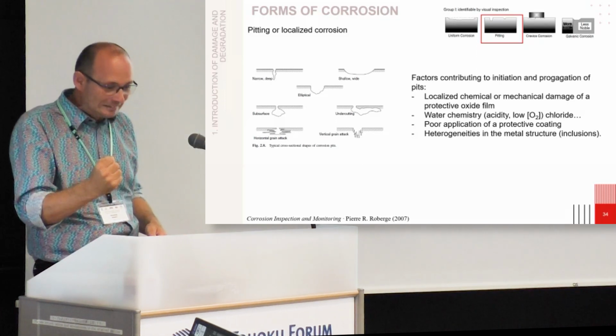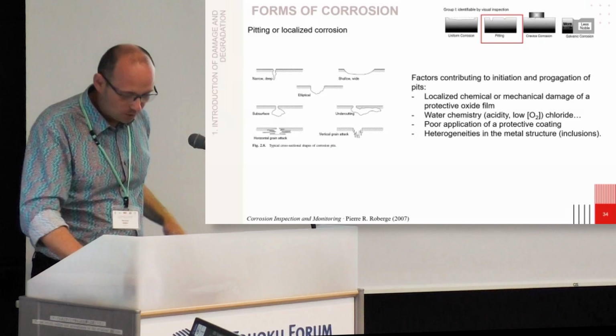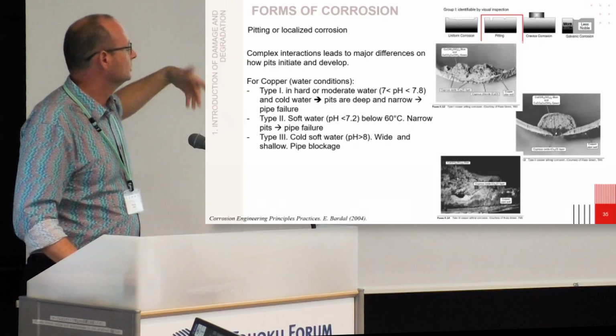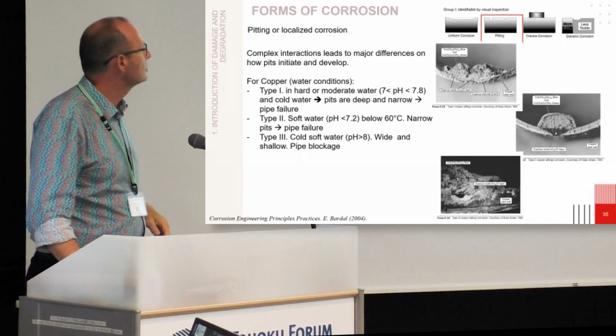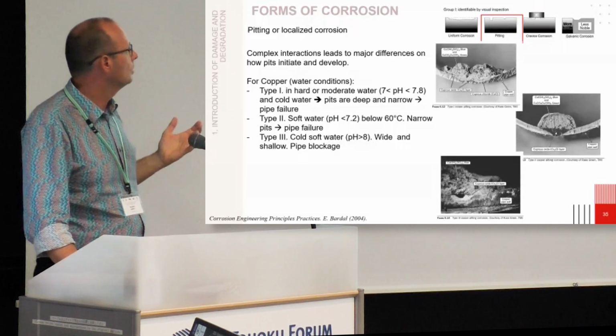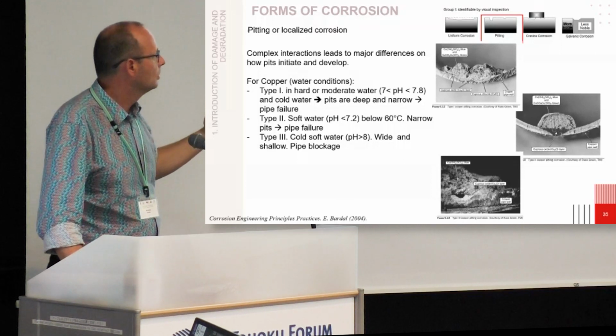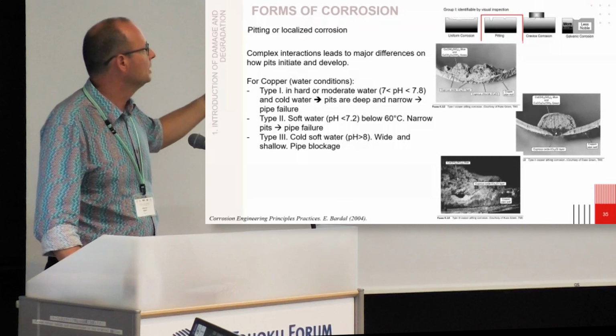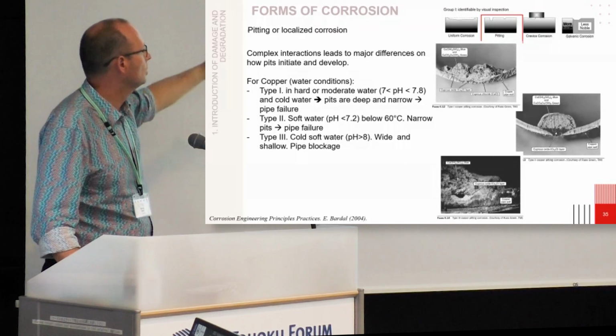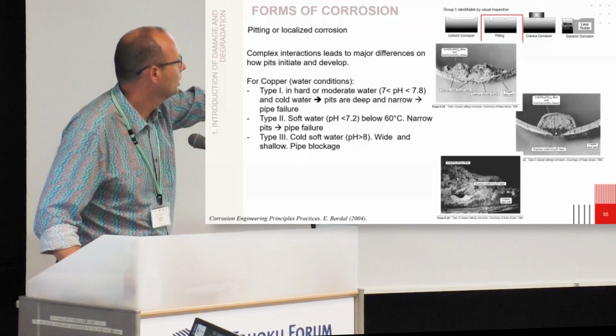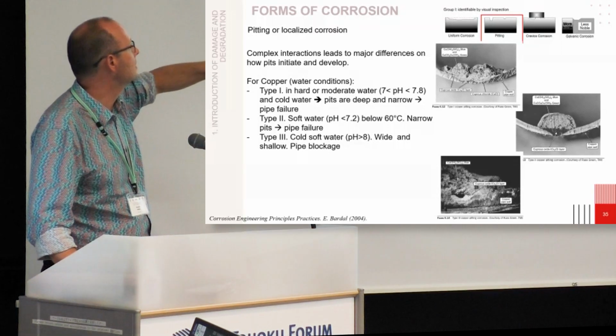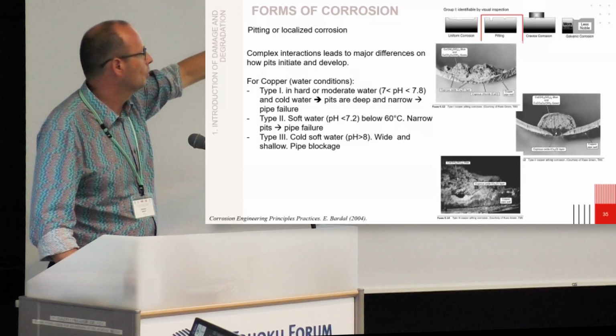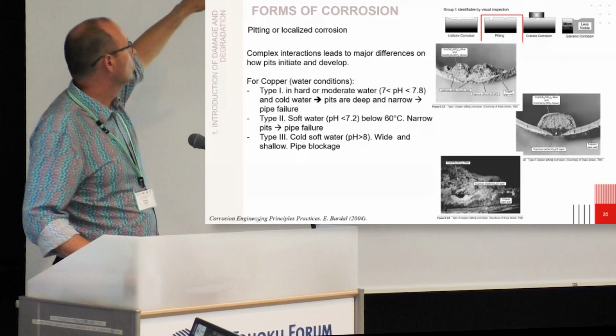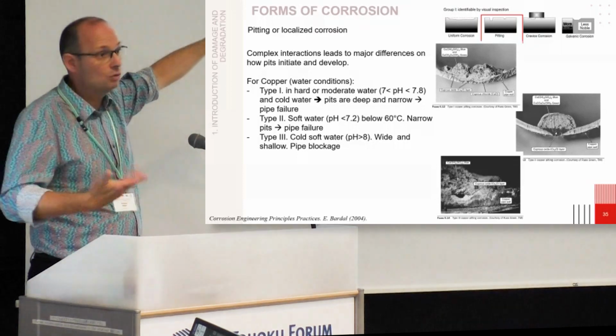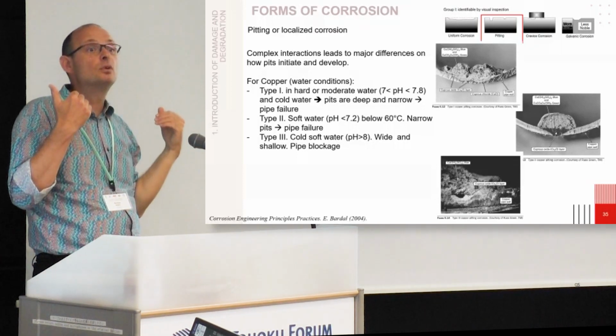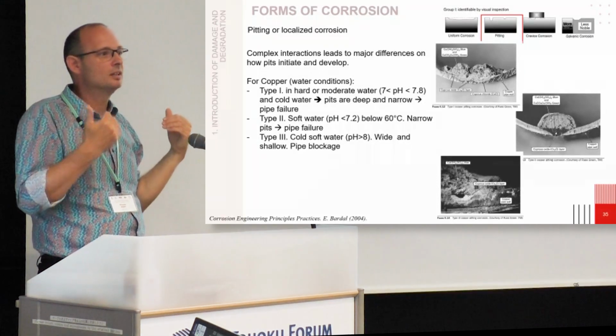Two minutes. Wow. Okay. So I will go fast because after this is only a demonstration. And here it's to show you that it can be quite difficult. Okay, pits and the consequences of corrosion at the pit. You can have information about what was the environment. This is a copper pipe in a piping system. And actually, if you look at the degradation, you look at the product that you have, and you can go to the history of the pieces. That's also very interesting. It's kind of expertise.